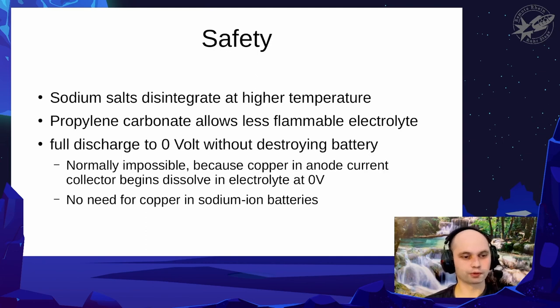The other point in safety is that you can discharge a sodium ion battery to 0 volts because there's no copper in the current collector. The copper would normally dissolve into the electrolyte, and then the next time you start charging it after you fully discharged it, you would get copper somewhere in the battery, and that somewhere could be absolutely anywhere, and you can get shorts and absolutely destroy the battery like that. That's why lithium-ion batteries must never be completely discharged.